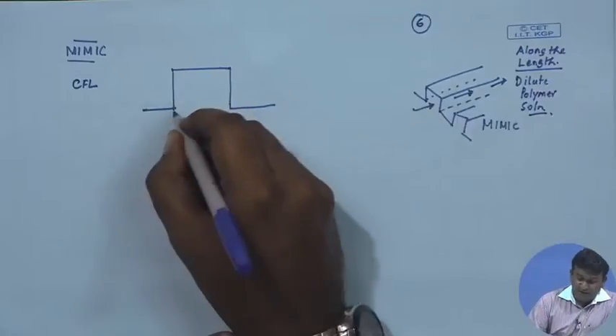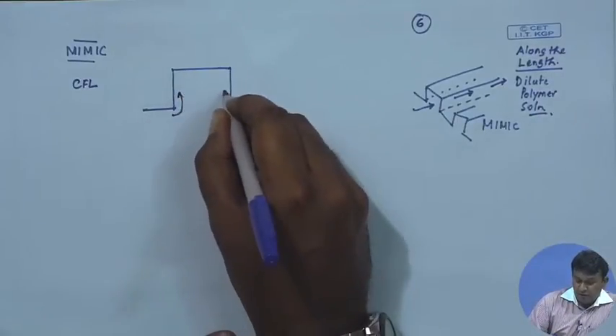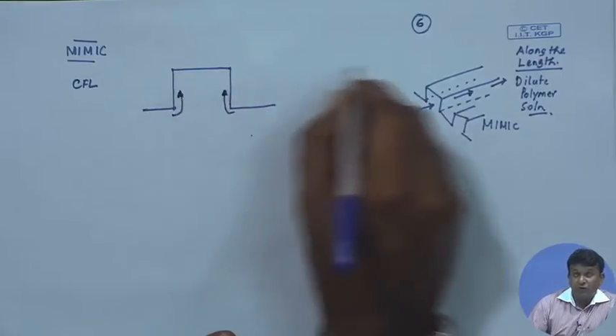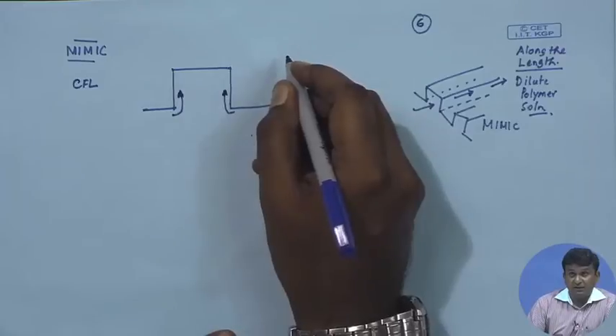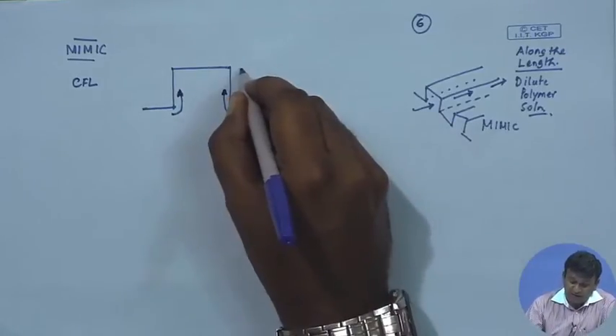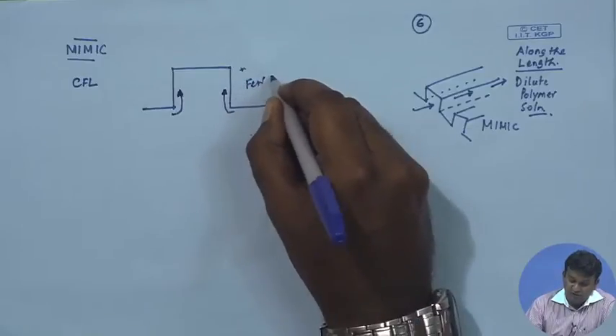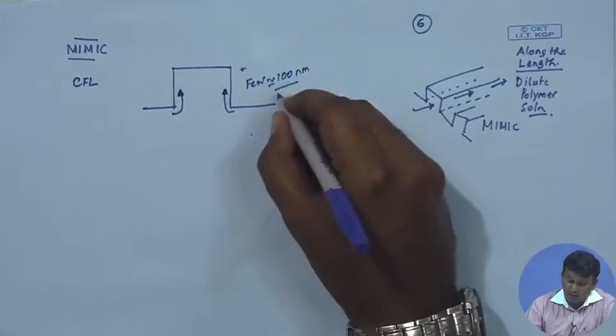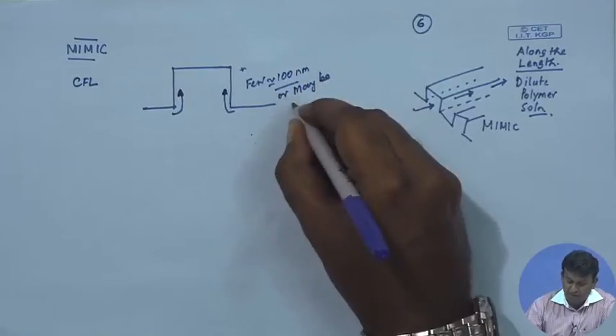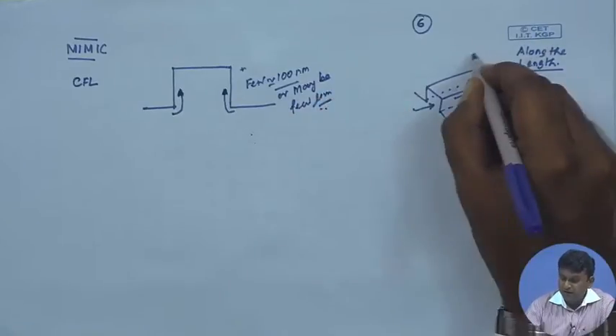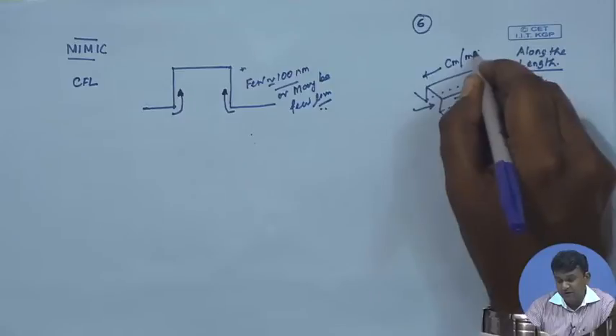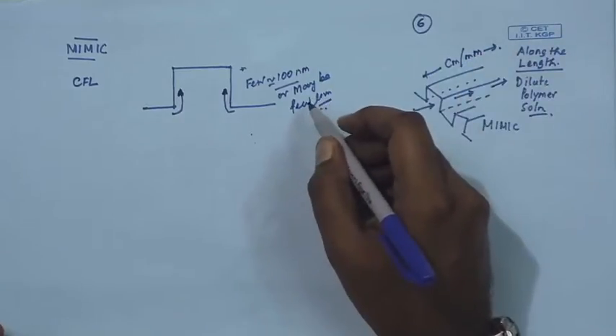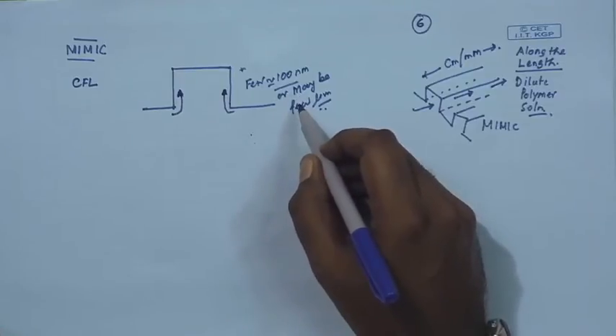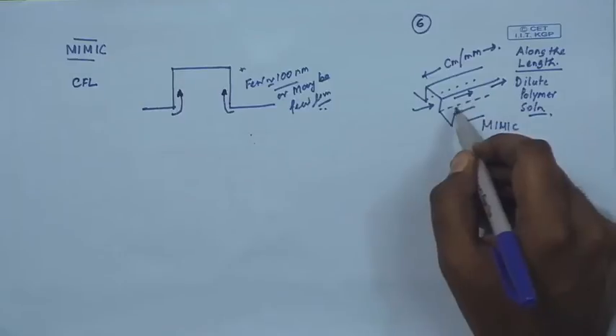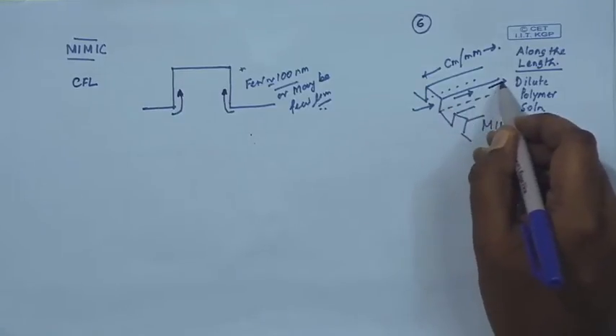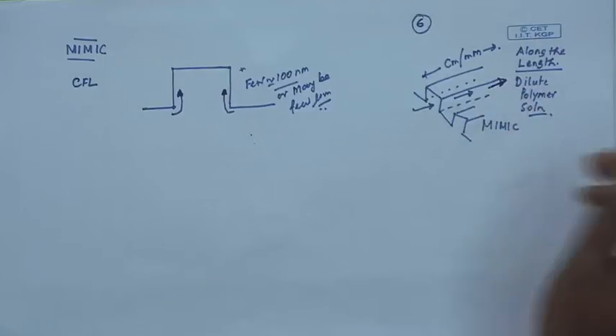Instead, what happens in CFL is it relies on capillary dynamics of the polymeric film, the softened polymeric film, which is in a liquid form, along the height of the channel. So, the immediate consequence is this height is a few hundreds of nanometer or maybe a few micron, and this is centimeter, at least millimeter. So, you are reducing the travel path of the fluid by capillary dynamics, and therefore the problem that we had in MIMIC, like the capillary driven velocity becoming too less and mold filling not taking place, all those problems are eliminated.